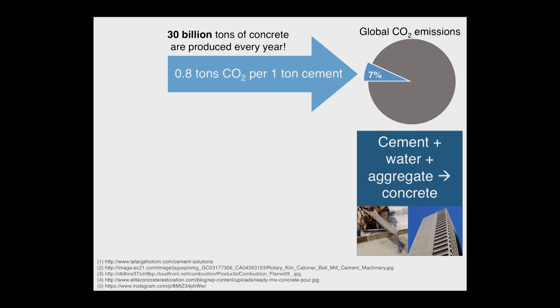Cement, the main component that makes concrete and makes it strong, emits approximately 0.8 tons of CO2 for every ton of cement produced. This adds up to over 3 billion tons of CO2 every year, or roughly 7% of global total emissions.